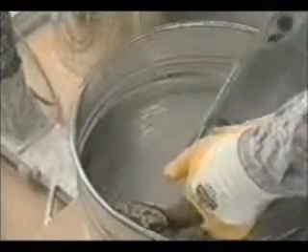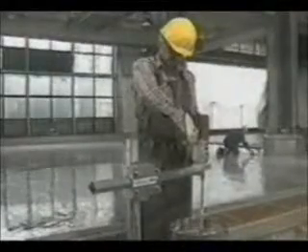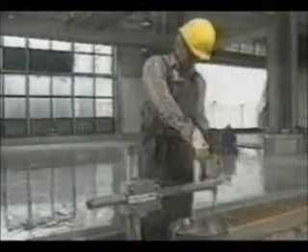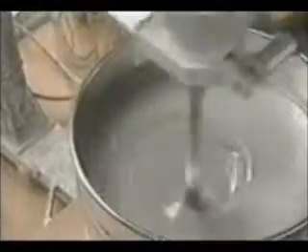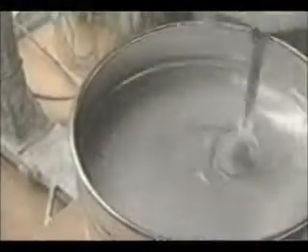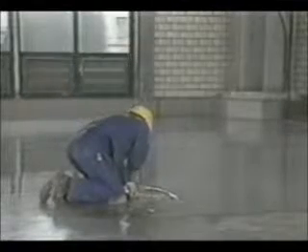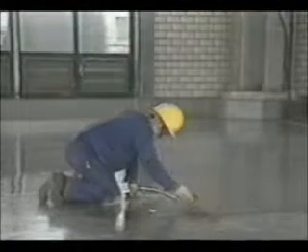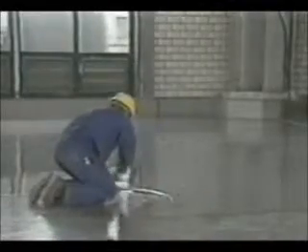The key feature of the subsequent intermediate coat is its flexibility. This can be varied as required through the choice of the Desmodur and Desmophen components. The result is effective crack bridging in a highly durable coating system. The ductile intermediate coat is applied by trowel to produce a film thickness of 2 millimeters.